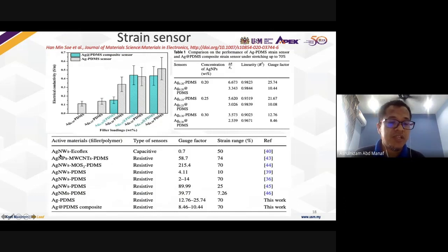There is a nanowire mixed with PDMS, and with Ecoflex it can act more as an insulator. The ratio, that is the filler loading percentage, we changed from 0.1, 0.15, 0.2, 0.25, and then 0.3, to improve the conductivity.